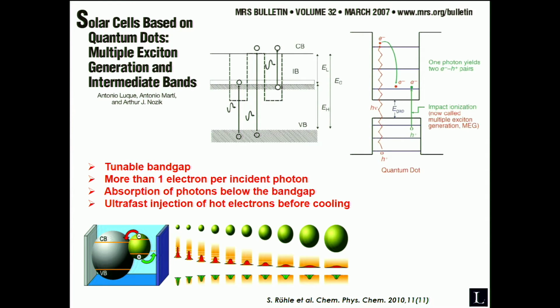You can claim that there are intraband transitions in your system, so you can absorb two low energy photons to get one electron produced, while in other materials, if you don't have such bands, the low energy photon is lost. People also claim the possibility of so-called multiple exciton generation, in the sense that you can absorb a single energy photon, and the relaxation of a high energy electron gives rise to the formation of a second electron.